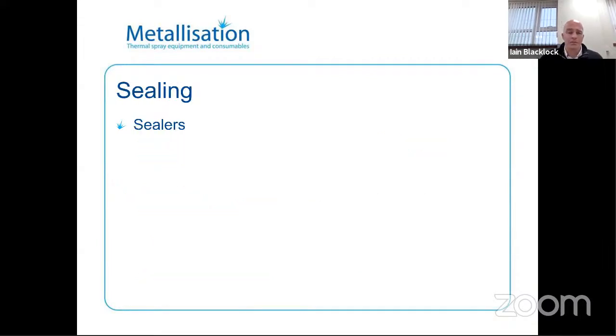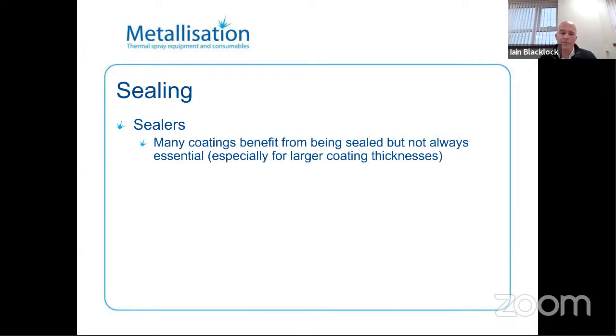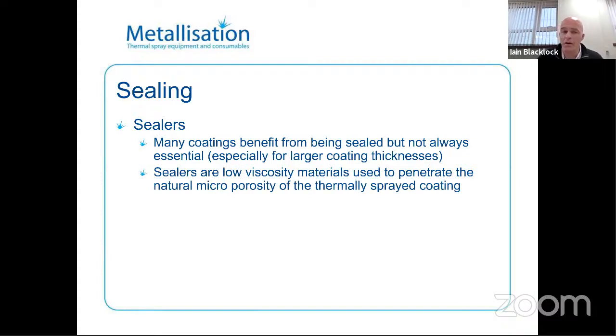So for sealing, sealers: many coatings will benefit from being sealed, but they're not always essential. If you've got a very thick coating, generally you get micro porosity within the coating, but the chances of that being through porosity is minimized or removed. For thinner coatings, 100 microns up to 250 microns, generally you'd use a sealer coating. Our sealer coating is a low viscosity material. It's like a thin down paint. It's applied onto the thermal spray coating.